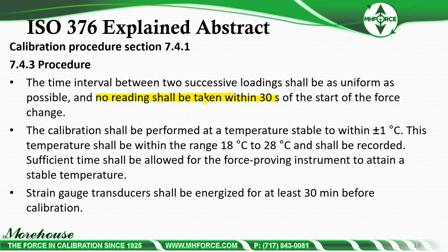And if you're sending your equipment to a lab that's just going up and going down and they're not waiting 30 seconds, they are not following the ISO 376 standards. So the other part of the standard: the calibration shall be performed at a temperature stable to within plus or minus 1 degree C. This is the same as E74.